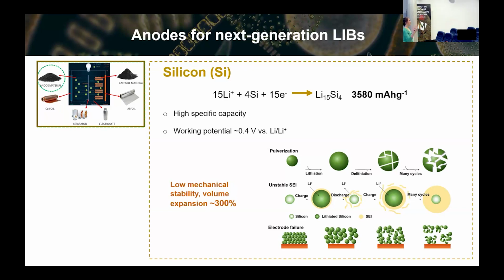And also the use of coatings on the material, just to restrain a bit how much it will expand. Another possibility comes from the protocols you use for cycling. Instead of going to the full lithiated state, you can stop before it is fully lithiated, so you expand a bit less.